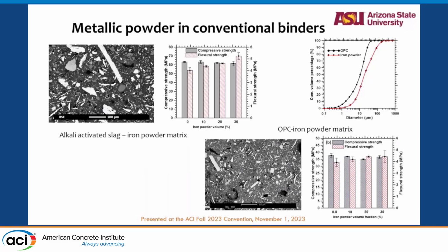And here the basic theme was to use these iron powders to make the concrete conductive, so that we can most probably use it to sense strength. But initially, we have to characterize the mechanical properties. So what we did was we tried two different types of mix. One is an alkali activated slag mix and another is a normal OPC concrete mix.